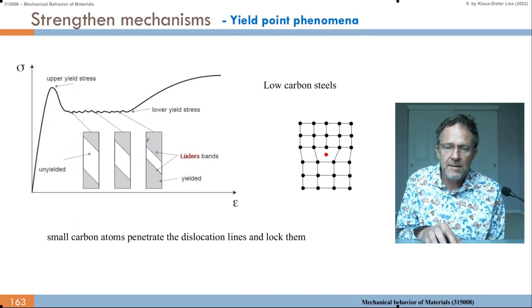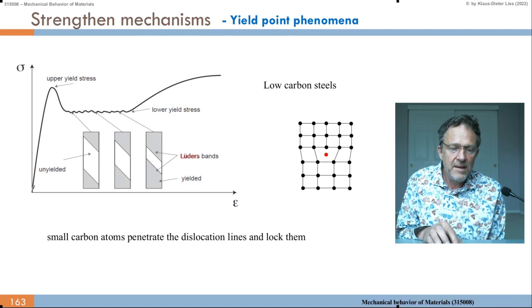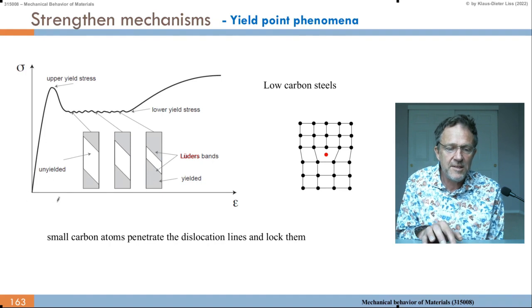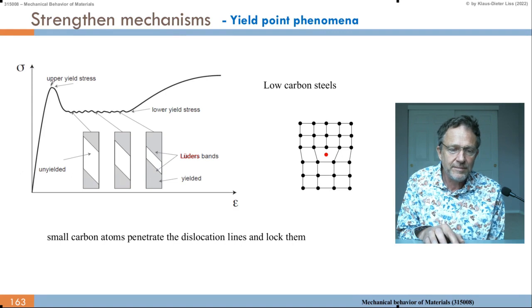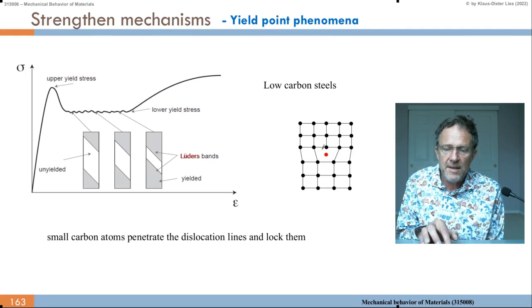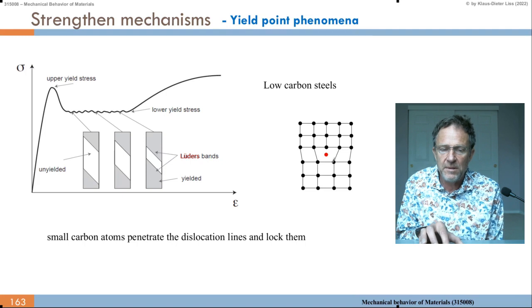That's another interesting phenomenon here, the Lüders band. So we have the perfect crystalline material, annealed polycrystalline material here, and then we pull, so we get elastic strain and a yield. Then it yields, and when yielded, it becomes weaker. It becomes weaker because here in that low carbon steel we have carbon atoms sitting at the dislocation. And that's what I said before, with solutes you can have segregation of the solutes, or segregation of the carbon in the strain field of the dislocation.